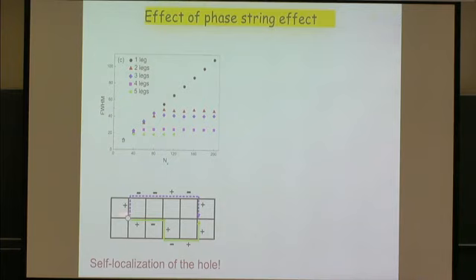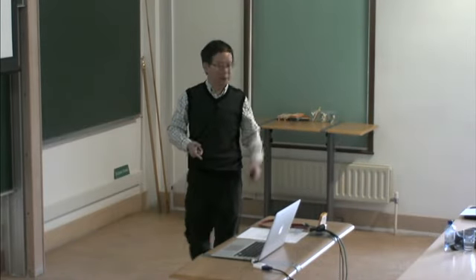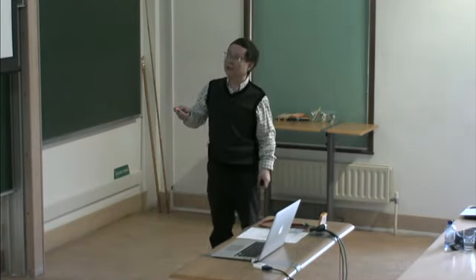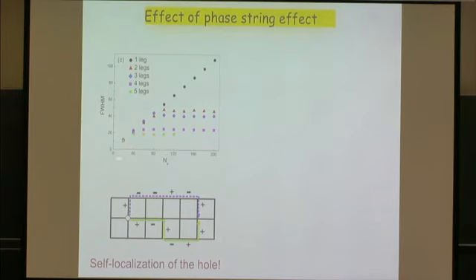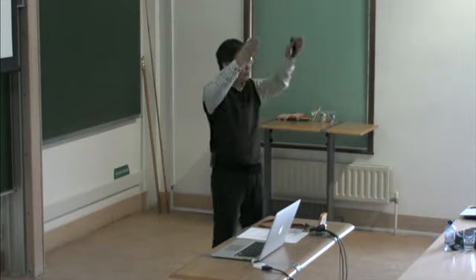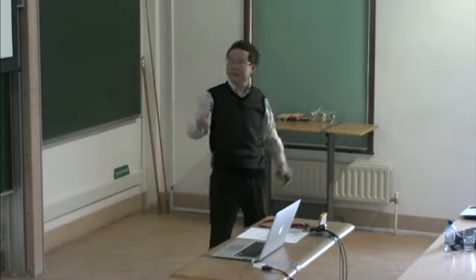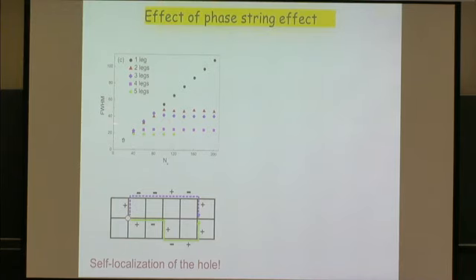So for finite size, Nx is the size of this ladder, and the charge would localize, of course, bounded by this length scale of the ladder. For one dimension, when the chain's length increases, the width of the charge increases linearly. That, of course, is the mobile Luttinger liquid behavior. But for 2-leg, 3-leg, 4-leg, 5-leg ladders, something happens: when Nx is large enough, it becomes saturated. In other words, it becomes localized, insensitive to the sample size. And this localization length is actually very large, 50, 30. So it's much larger than what exact diagonalization can get access to. But still, it shows that very flat structure.